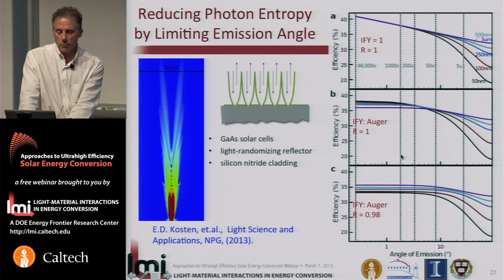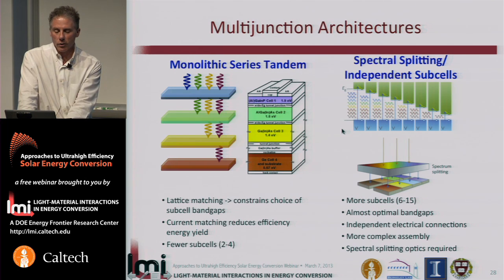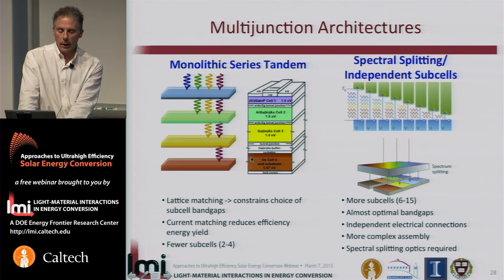Finally, before finishing, I'll just mention that the big opportunity for increase in efficiency is to mitigate the thermalization losses. Conventionally, this has been done using tandem multi-junction solar cells, with a number of absorbers which are constrained by the need to do epitaxial growth of all of the layers in an optically in series stack here. In fact, these cells are almost always in monolithic form, electrically in series. As a result, that offers some constraints on the power conversion efficiency of a cell compared to an optically and electrically in parallel design in which, as I mentioned earlier, light is split into narrow spectral bands impinging on each cell.